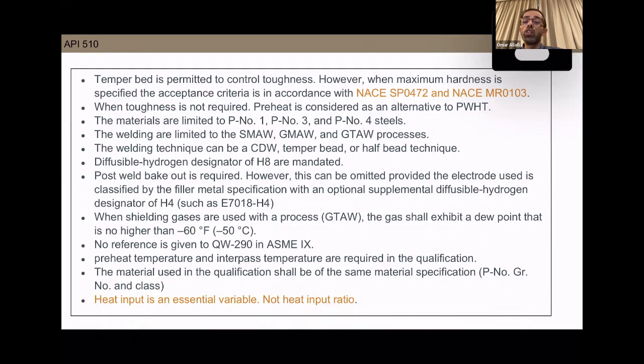Diffusible hydrogen is H8. Post-weld bakeout is required and can be omitted when using H4 hydrogen designated electrodes. When shielding gas is required, the gas shall exhibit a dew point that is no higher than -50. This is for GTAW. No reference is given to QW-290. Preheat temperature and interpass temperature are required in the qualification. The material used shall be the same material specification, P-number, as well as group number.